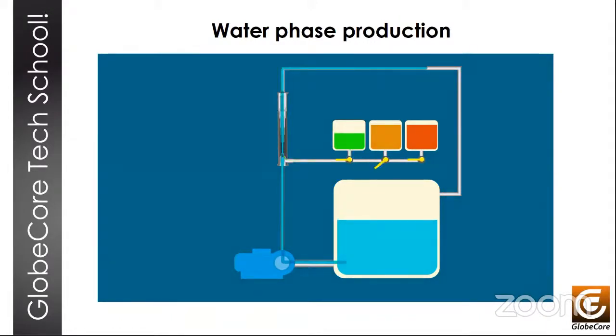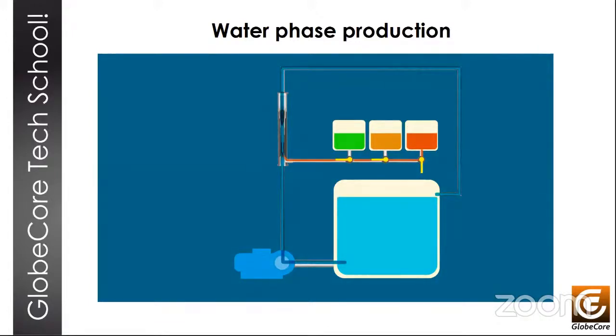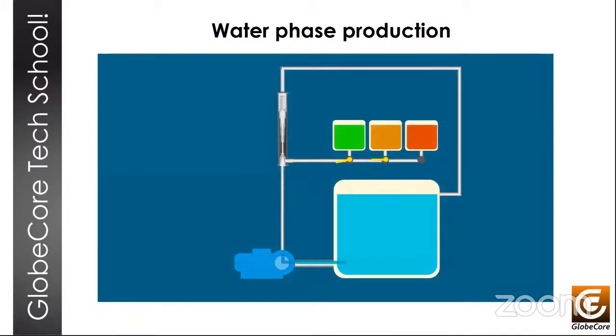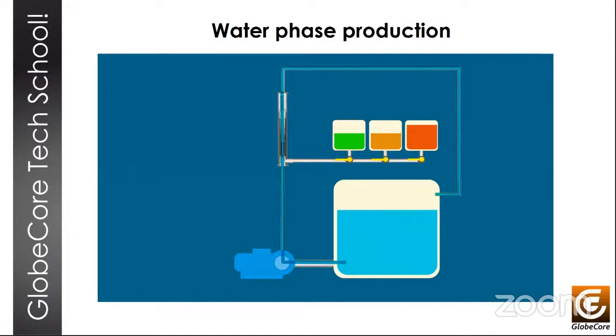Another obvious advantage of this technology lies in the fact that the plants can work longer from one batch of water without the need for large containers for blending, since the concentrate of the water phase is increased in volume by as much as 5 times before entering the emulsion mixer. In addition, the mixer allows taking some load off the mill, which serves mainly to stabilize the already mixed emulsion. This is reflected both in the quality of the emulsion obtained and in the service life of the mill, which is extended quite noticeably.